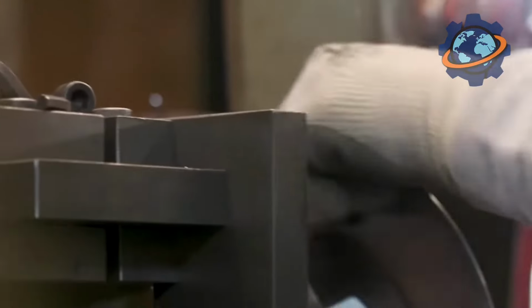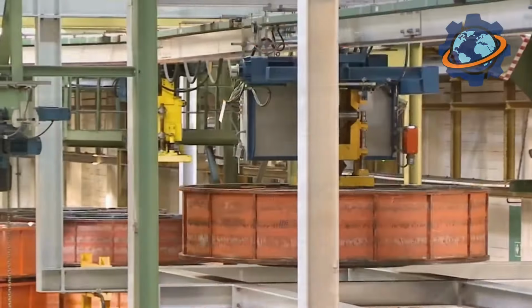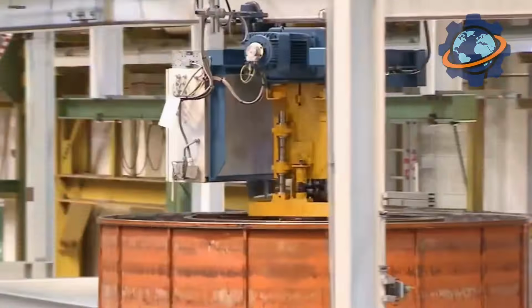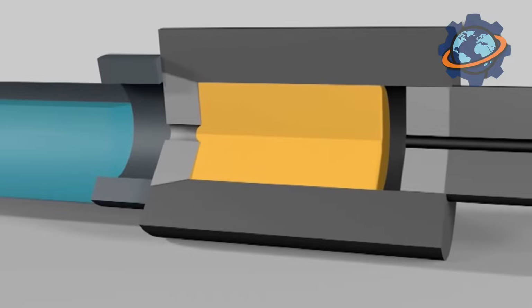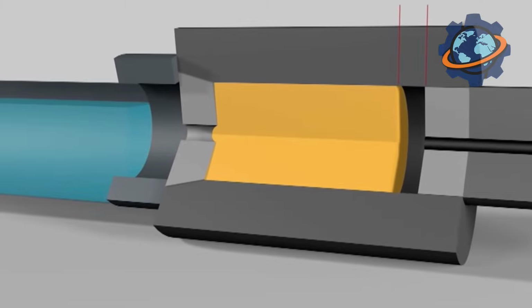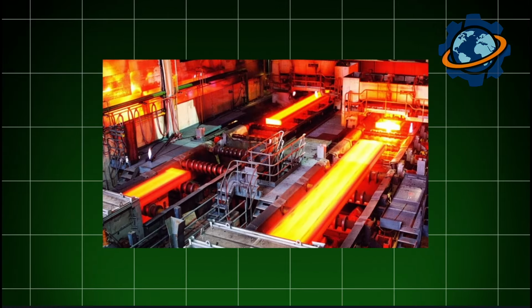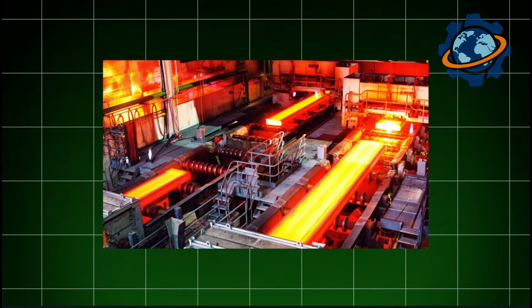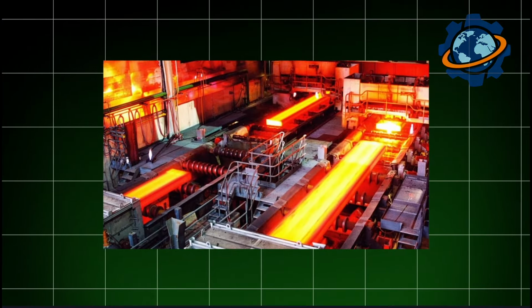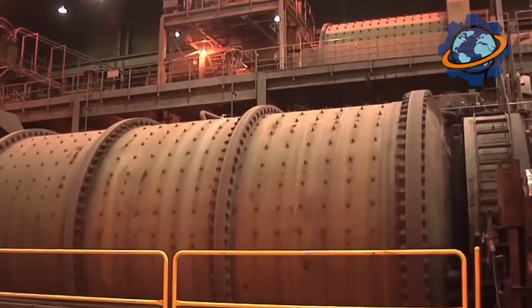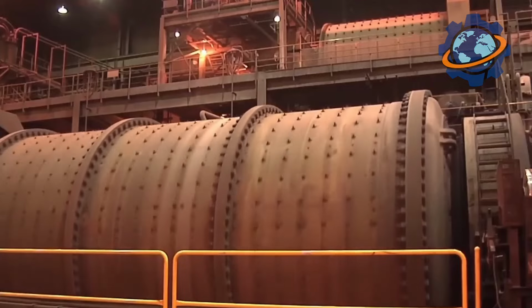The red-hot slab enters between rolls, which squeeze and roll it. The slab gets thinner and longer. It passes through the next pair of rolls, even thinner, dozens of times. An 8-inch thick slab becomes a sheet 1 to 2 millimeters thick, and its length grows from 33 feet to over half a mile.